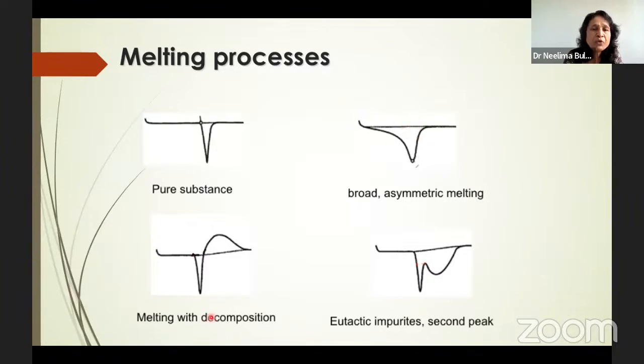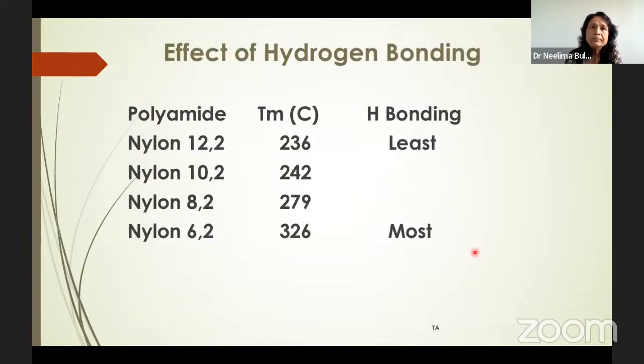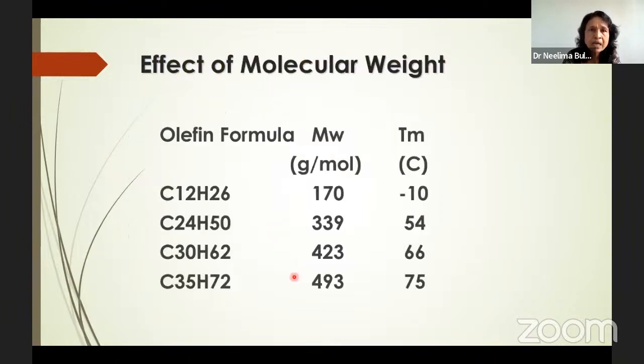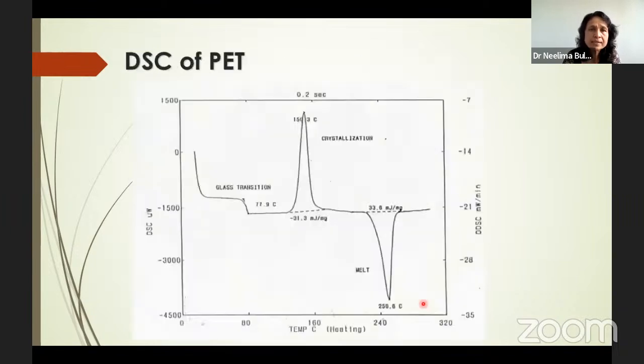and the material is not that pure. If you are getting this type of curve in DSC, after melting there is a decomposition, you can read that. And if you are getting this type of curve for your pharmaceutical sample, then you can say that eutectic impurity is present in your sample. So the effect of hydrogen bonding: if you increase the hydrogen bonding, your melting increases. If you increase the molecular weight, your melting is going to increase. So this is how a typical DSC curve looks.